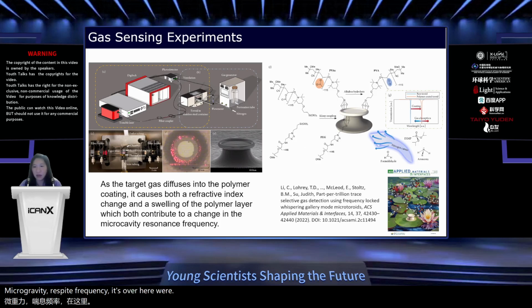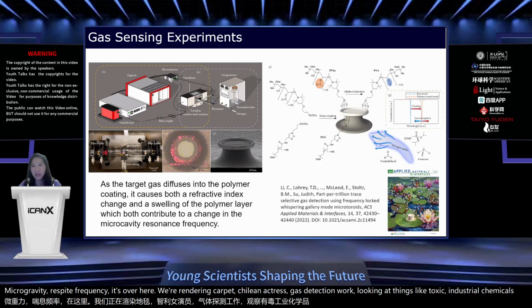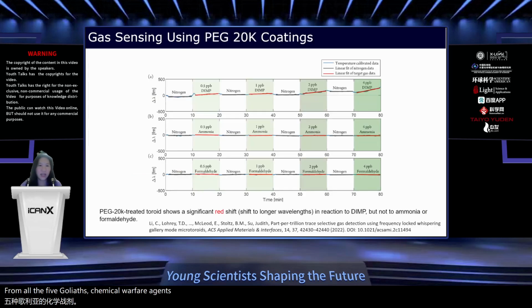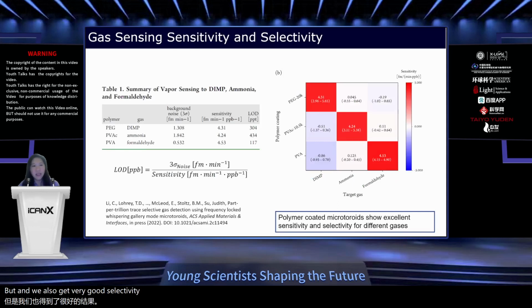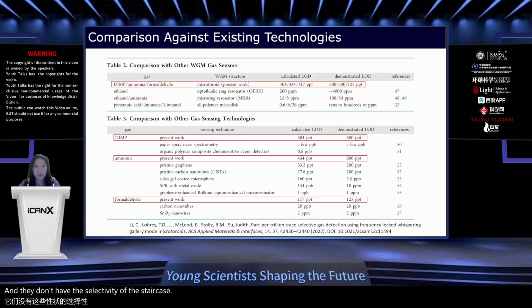And so here we're doing part per trillion trace gas detection. We're looking at things like toxic industrial chemicals like formaldehyde, ammonia, chemical warfare agent surrogates. So we get shifts to longer wavelengths in reaction to DIMP, which is a sarin surrogate. And then we also get very good selectivity of our gases. This is actually better performance than anything out there, with the exception of pristine graphene, which they do their experiments in vacuum, and they don't have the selectivity from these different coatings. And it's certainly better than any other whispering gallery mode gas sensor that's out.